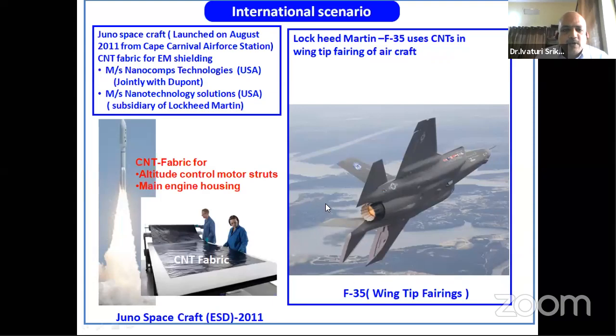Now, if you see globally what people are doing, people have made CNT fabrics. I've shown you some CNT webs in CVD synthesis, CNT based webs, carbon nanotube webs. Those webs were pressed between two rollers and made into a fabric. This is a continuous CNT fabric. And they are using this in the topmost layer of the polymer composites to get the conductivity. These kind of things are used in some of the aircrafts globally. So this is a global trend.